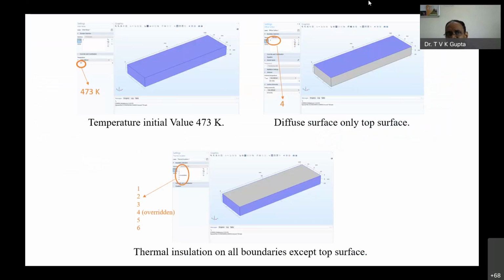Now, initially, for every component we have done preheating up to 200 degrees centigrade, and then we deposited, so that the distortion is as minimum as possible. In fact, in an aerospace component, distortion is not at all allowed. They don't allow any distortion. So for that, you need to do a lot of homework and optimize a huge number of parameters. Then only will you have minimum distortion, right?